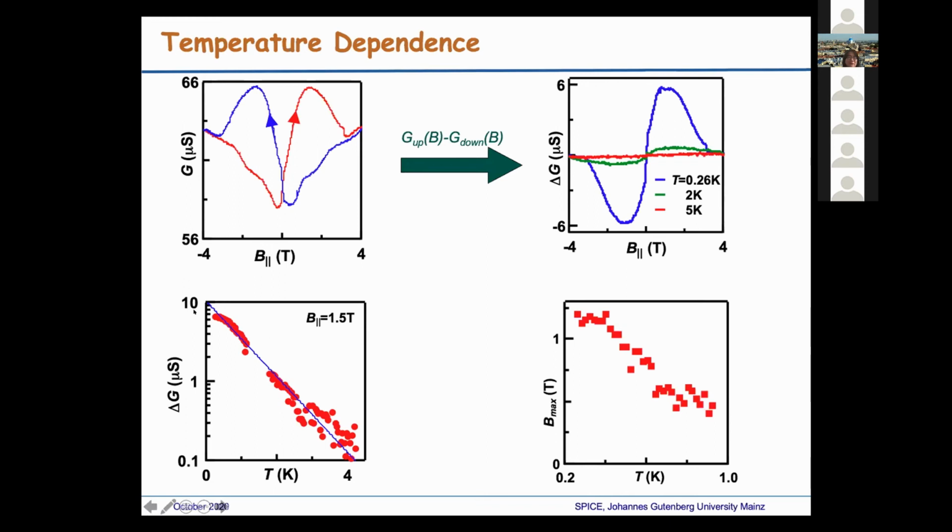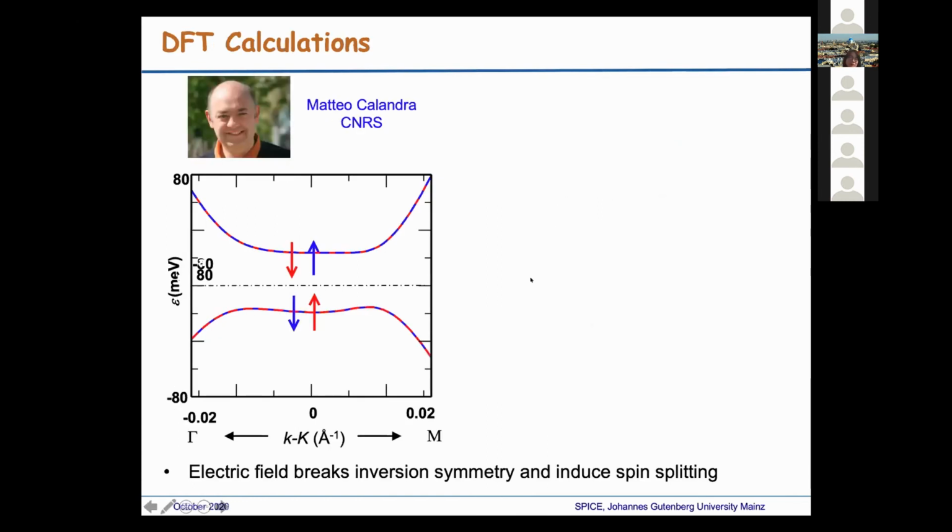Here we try to parameterize the hysteresis as a function of temperature, and it shows that the coercive field roughly goes down with temperature, almost linearly.